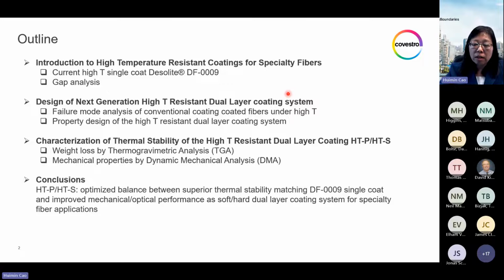But as a single layer coating system, it does inherit some intrinsic performance gaps, which I will show a gap analysis next. And you will see the solution to overcome these gaps is to develop a dual layer coating system. However, due to the high technical challenge for the dual layer coating system to match the thermal stability of a single coat, especially with the much softer primary coating, this attempt has not been very successful in the past.